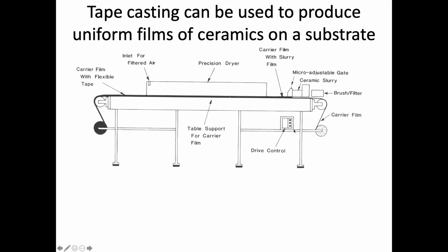And so typically these things are quite long tables. And the main portion of it is sort of a conveyor belt, which allows the film, the substrate, to move. And what it does is we have the ceramic slurry. So this is another application where we have to have a liquid version of the ceramic. So we have the ceramic powder in some type of liquid that's dispersed. So you'd have to have typically some type of dispersant agent if it doesn't disperse on its own. And so we have the slurry in this chamber here.